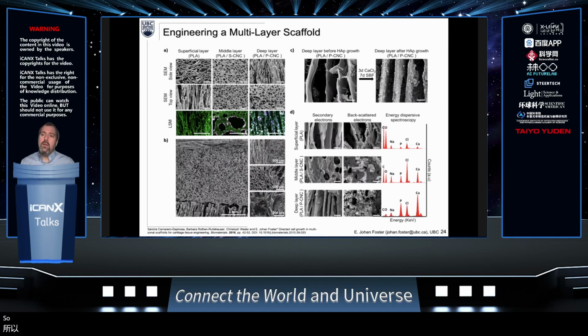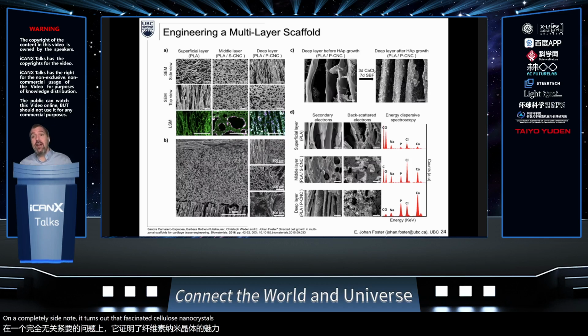So we were the first group that actually created cellulose nanocrystals with phosphates on them. And that was simply to be able to get those calcium phosphate pre-growth of hydroxyapatite in that bottom layer so we could integrate it with bone. On a completely side note, it turns out that phosphated cellulose nanocrystals were actually very advantageous in their thermal properties. So I'll tell you about that a little bit later. But originally we had created them simply to have phosphate groups on the surface that we could pre-grow hydroxyapatite.